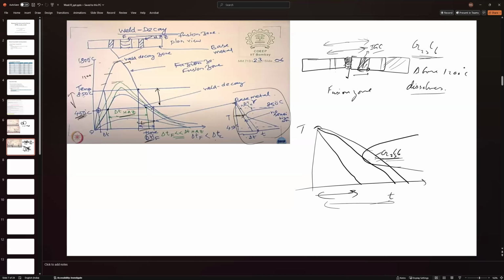So this happens particularly in the region where the temperature doesn't cross 850 degrees Celsius at the hot end, and at least reaches 450 degrees Celsius. So there will be a region where you still have gradients, and close to this region you will have a maximum amount of sensitization. As you move away, your sensitization will decrease.